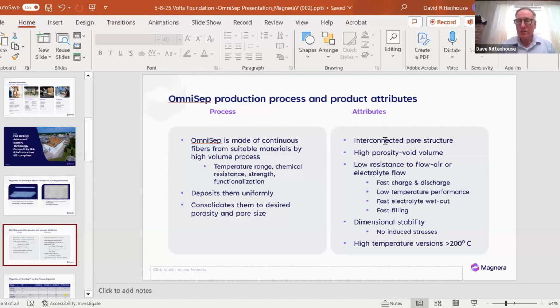This structure gives an interconnected pore structure, high porosity and void volume that provides a low resistance to airflow or electrolyte flow, giving fast charge and discharge, and low temperature performance because the thickened electrolyte can move through the separator more easily. It also gives fast electrolyte wet-out, and that is important for things like fill rate, and dimensional stability, because there are no induced stresses caused by the stretching that I described earlier. We have versions that are temperature stable over 200 degrees.